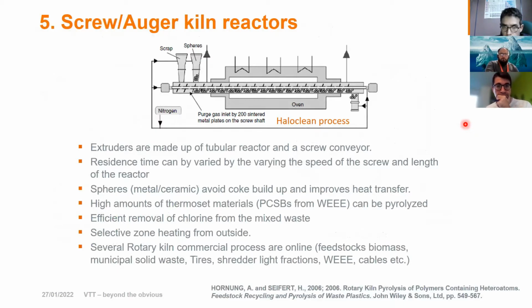So this is one example of a screw reactor called the Haloclean process from Germany. In this type of reactor, the extruder is basically made up of a tubular reactor. This is a tube that has a conveyor inside, or what you call a screw conveyor. The residence time in this one can be varied by changing the speed of the screw and the length of the reactor. So the time of the plastic degradation depends on how fast the screw is moving, because this will transport the material from this end to this end. And then it also depends on the length of this. So if it is of course longer, then you have a longer residence time for the plastics to degrade.